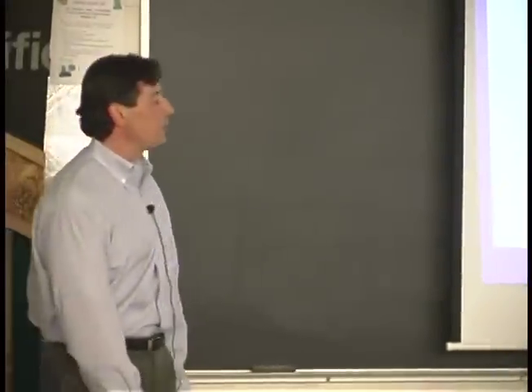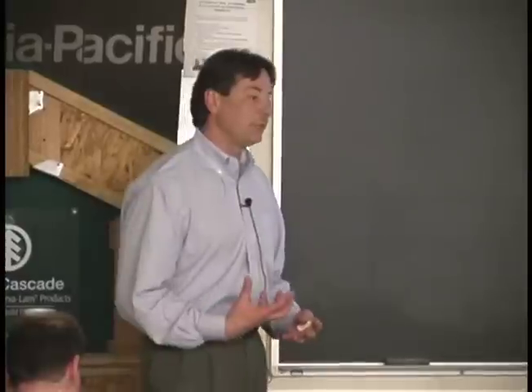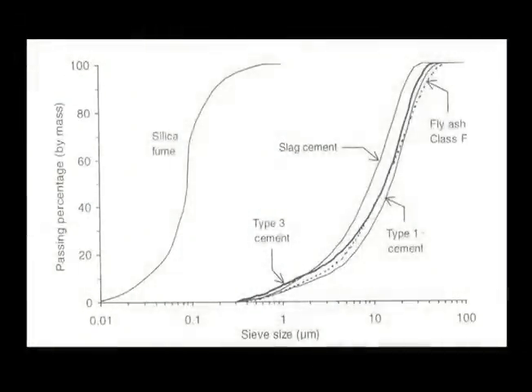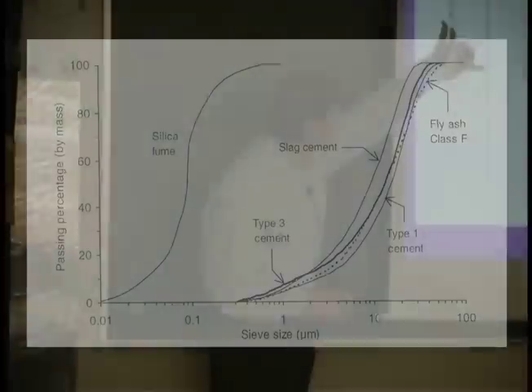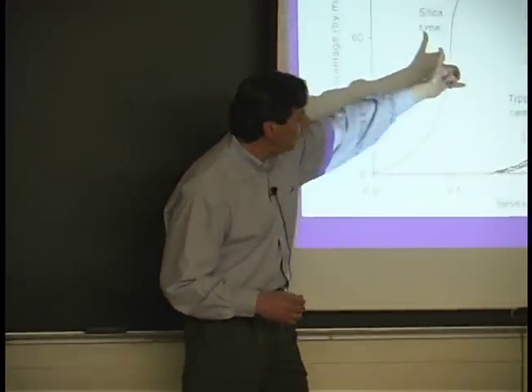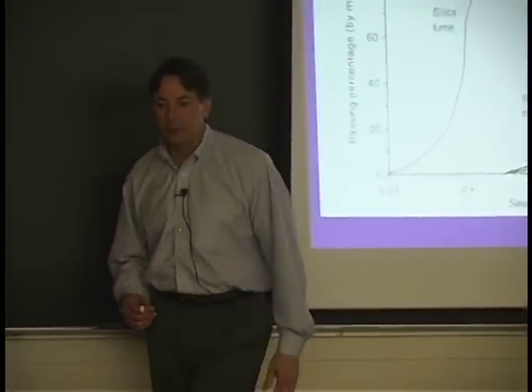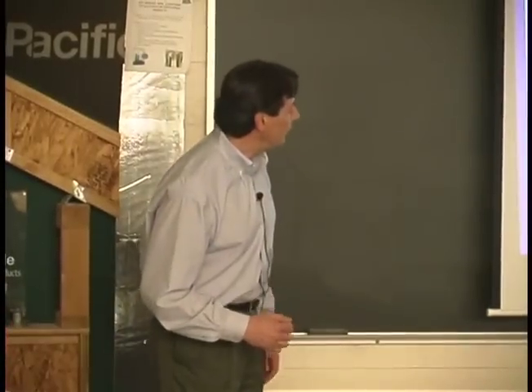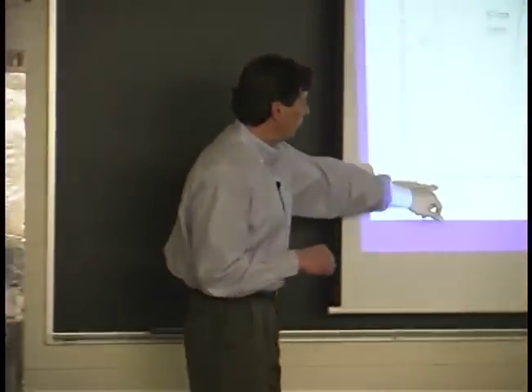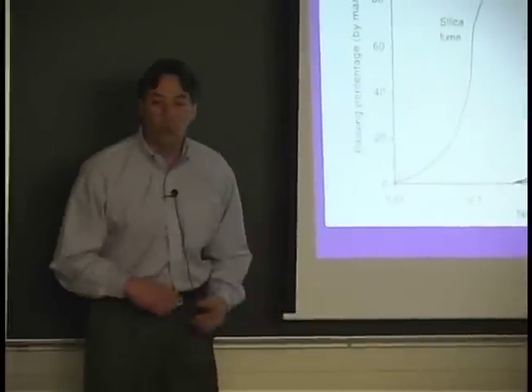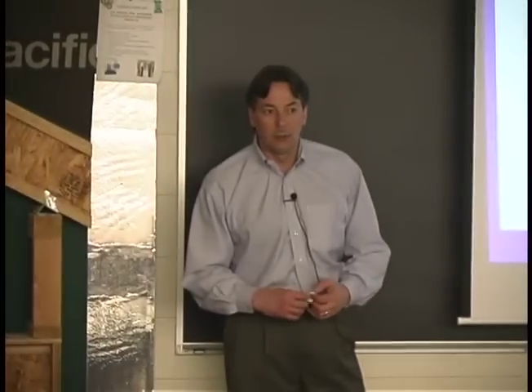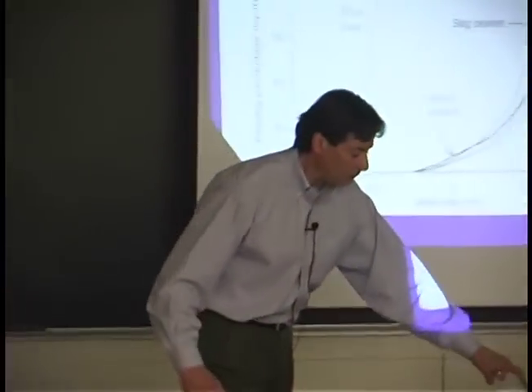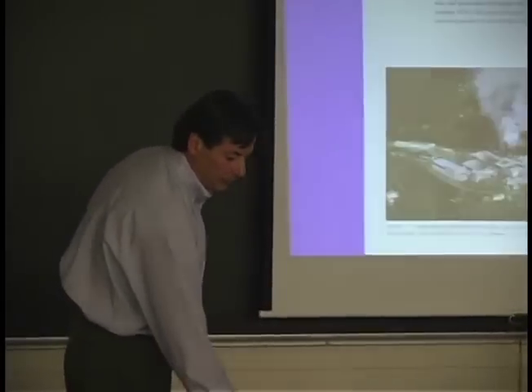Even though all those materials look like powders, there's some difference in those materials. Slag, fly ash, two different types of cement, they all basically have the same particle size distribution. If you look at the D50, 50% of the particles, the D50 is probably about 10 to 12 micron. The D50 of silica fume ends up being about 0.1 micron. Very, very fine material, 100 times finer than cement grains.